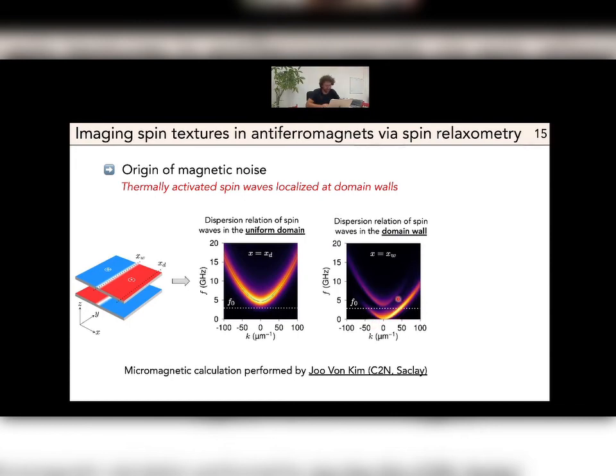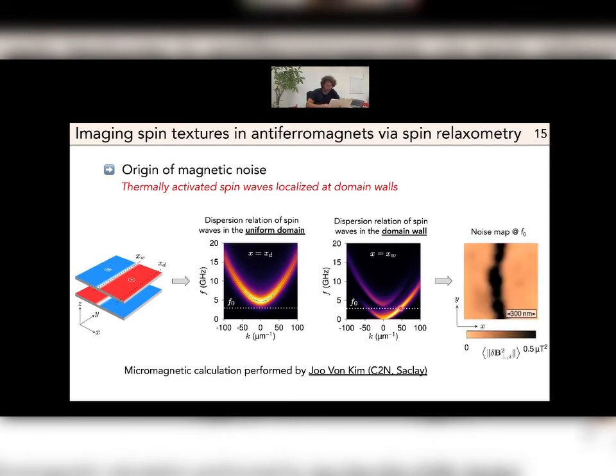If we go to the domain wall, at the domain wall the spin wave dispersion is gapless. This is something that is known both in ferromagnets and in synthetic antiferromagnets. As a result, you can populate some magnon modes here that will have a direct impact on the spin relaxation time of the NV defect. You can also calculate the noise map, essentially the strength of the noise, and you can see that the noise is indeed much stronger at the location of a domain wall. So this is essentially what we see in our experiments.